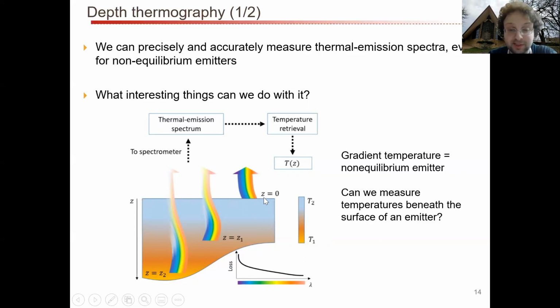So the thermal emission signal that's coming from the very top, all of it, at least that's emitted in the upward direction, is going to make it to your spectrometer, your infrared camera, and so forth. However, if you're looking at thermal emission from deeper into the material, some of that light is going to be absorbed before it reaches the surface. And of course, these things are connected because you also have an amount of absorption that depends on wavelength as well. So this is a complicated process, but essentially what you can do is take all that information, build a model, and try to retrieve the temperature as a function of depth as it actually was. So it's a metrology or measurement technique.